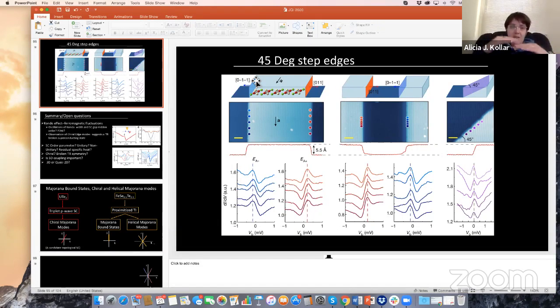And does it matter how big of a step it is, like if it's one layer or two layers or something like that? Yeah, there is some dependence on the height, but we haven't completely pinned that down yet. For example, here you can see that 45-degree step edges show you a particle-hole symmetric feature like this, which is centered right at the Fermi energy, inside the gap, of course. There's some indication that if you double this, then you might go to this scenario, but we haven't confirmed that yet.